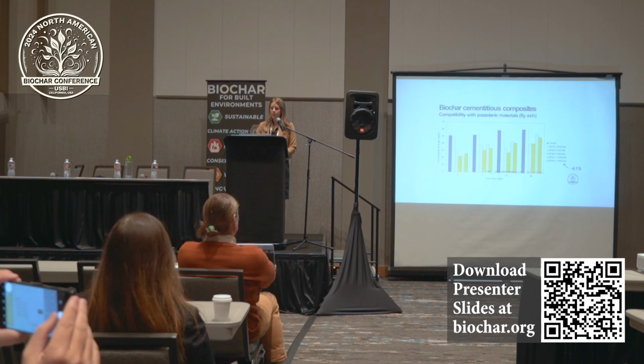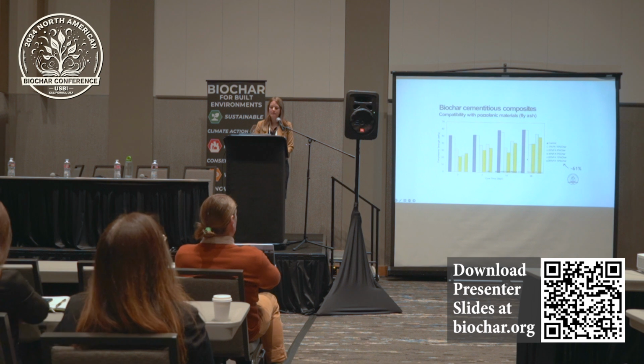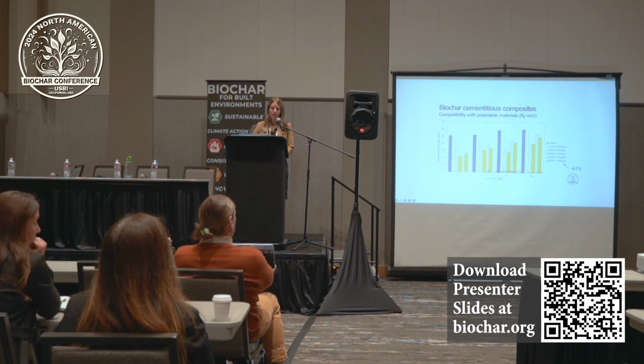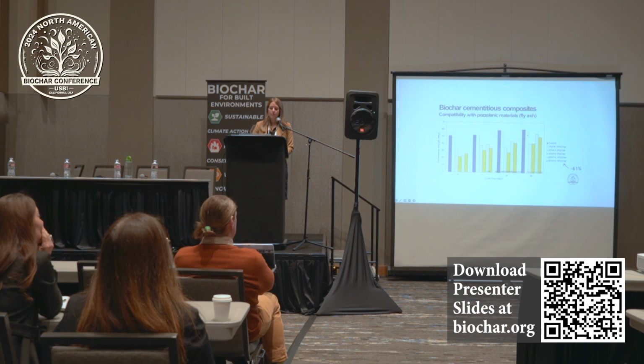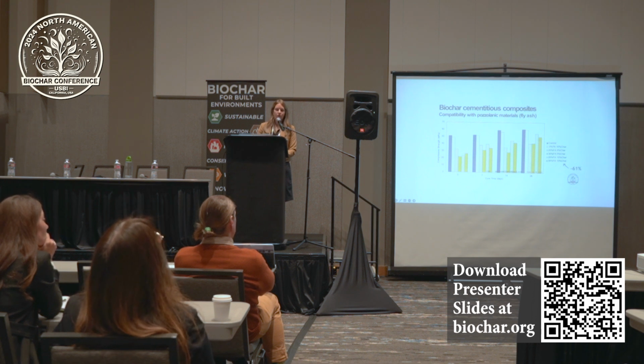So walking through from left to right here, we'll just focus on 28 days. We've got the control mix, so that's no replacements of cement in this dark gray bar. The dotted bars each have cement replaced with 10% biochar. And then the light yellow is 20% of the cement replaced with fly ash, and then the gold is 30% with fly ash. And then this is a combination of both, right?